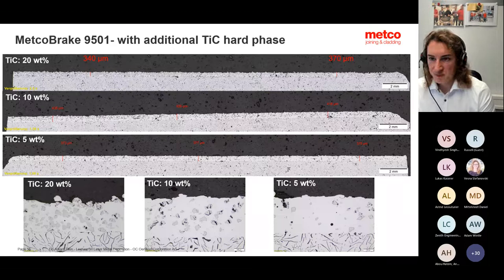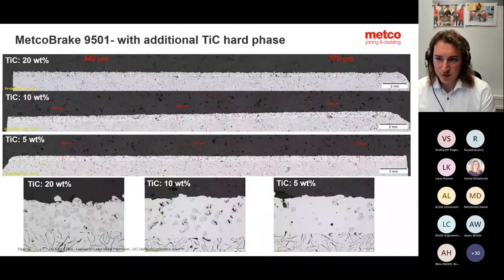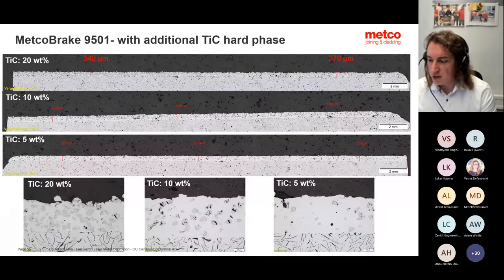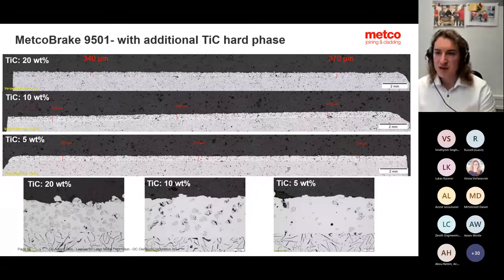Well, then we have the possibility to reinforce this type of material with, for example, titanium carbides. And also here, we do not need a bond or gradient structure formations, as these material features allow you to get up to 20% of titanium carbide, which is absolutely enough to increase your wear protection even further to interact with the surface with one layer deposition.